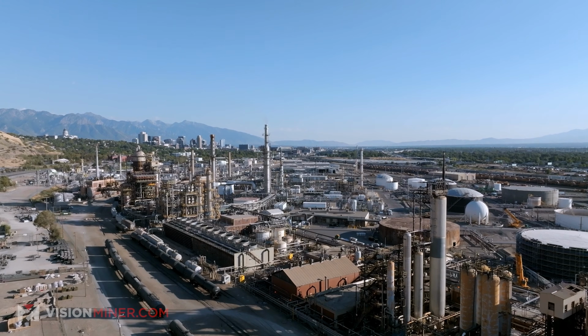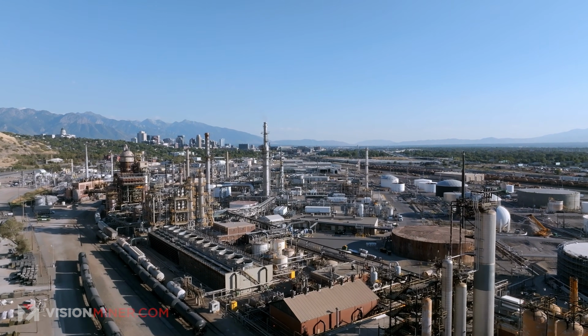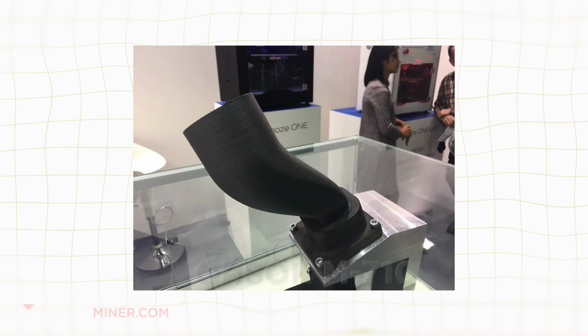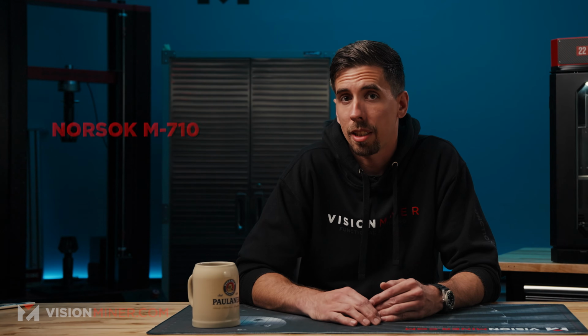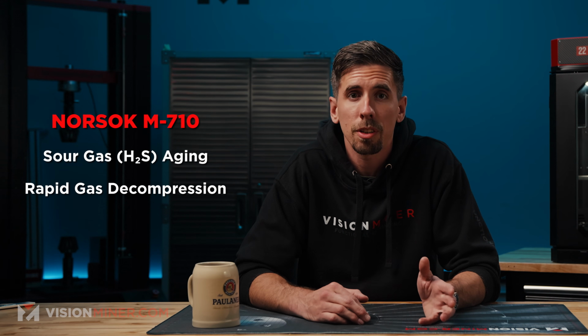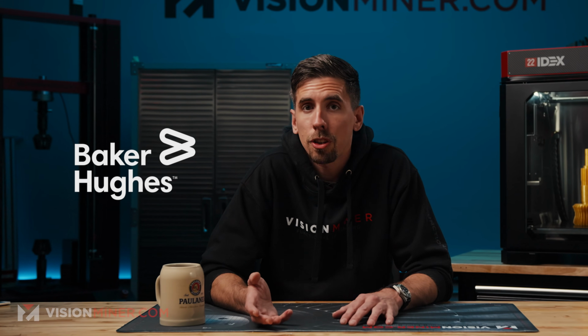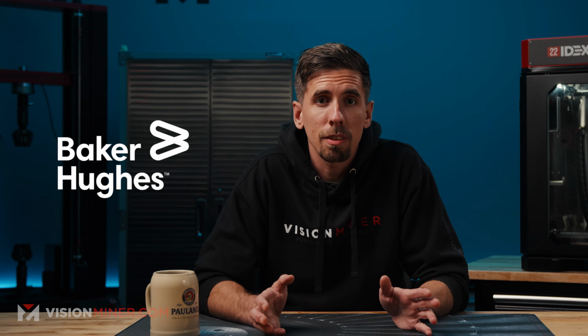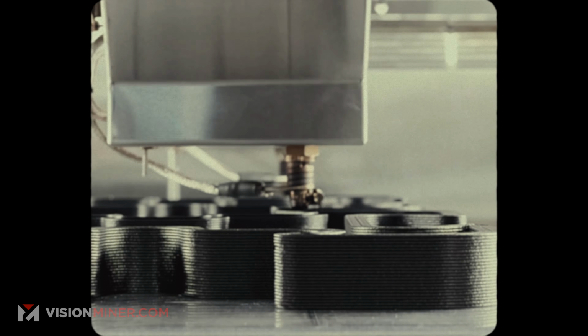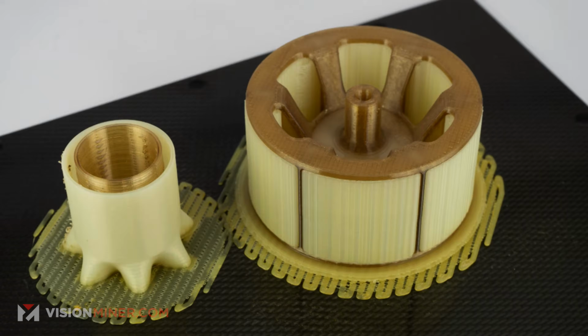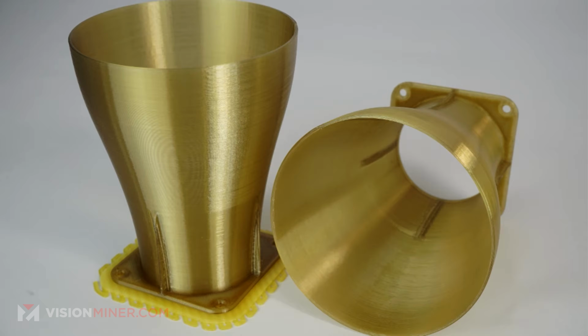And then there's Roboze, an Italian company based in Houston for oil and gas. I've seen them print massive carbon fiber PEEK rings, almost 3 feet across. It's absolutely nuts. Their PEEK is certified to NORSOK M-710, the Norwegian petroleum standard for non-metallic sealing materials. It tests for sour gas aging, rapid gas decompression, and compression set behavior. And then there's Baker Hughes. Their Houston AM Technology Center is 27,000 square feet of metal and polymer labs. The polymer side runs FFF, which is the same as FDM, just non-trademarked. There's over 1,000 part numbers they've developed, hundreds of qualified end-use parts currently in the field.